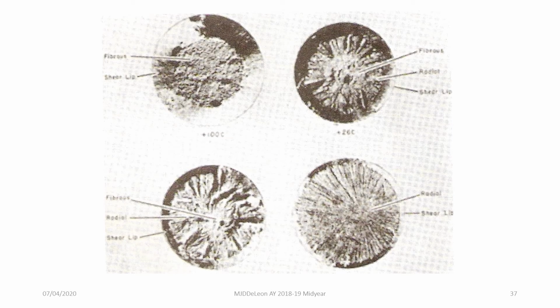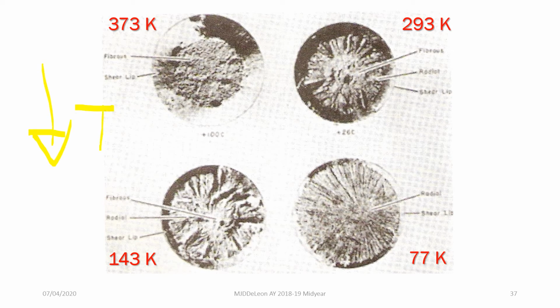So shown here in this slide is the same type of metal under the same strain rate, but ang nagkaiba lang is yung testing temperature nila. So from the top left to the bottom right, we are decreasing in temperature, so 373 Kelvin, 293 Kelvin, 143 Kelvin, and 77 Kelvin for the four different sites. And makita natin, as we decrease our temperature, nagkakaroon tayo ng more brittle na failure. So the brittleness of the failure can be shown by the size of the shear lip zone. If wala tayong masyadong makitang shear lip, essentially, little na lang yung plastic deformation natin before fracture, which makes it more brittle.